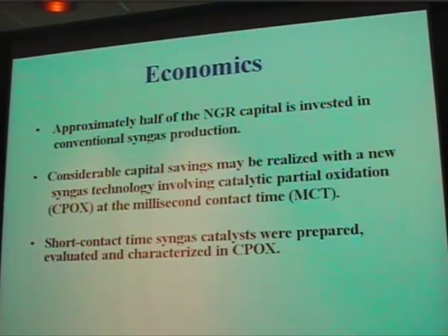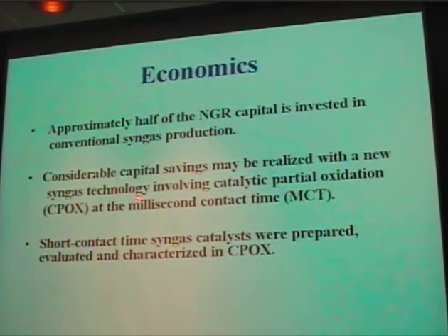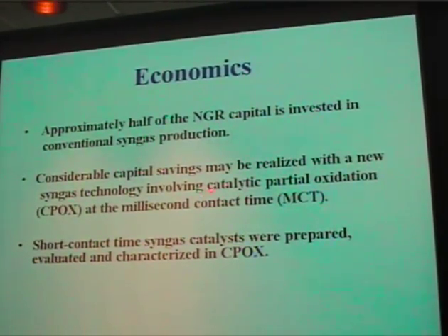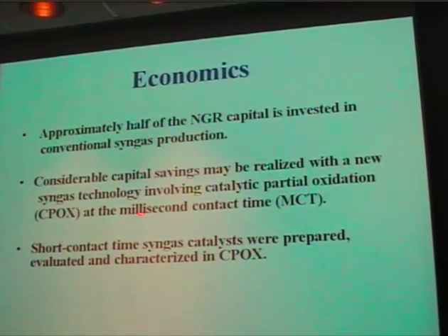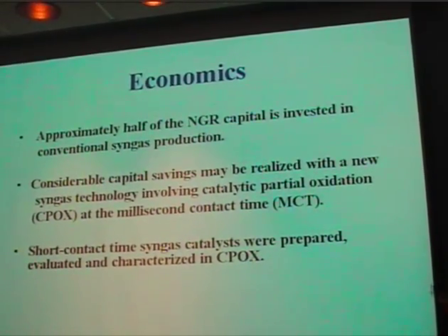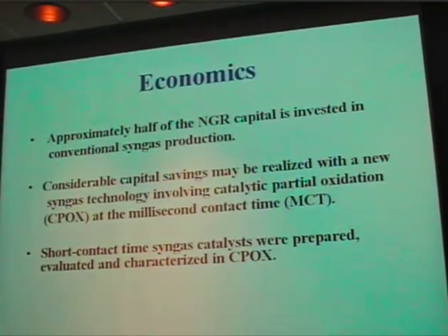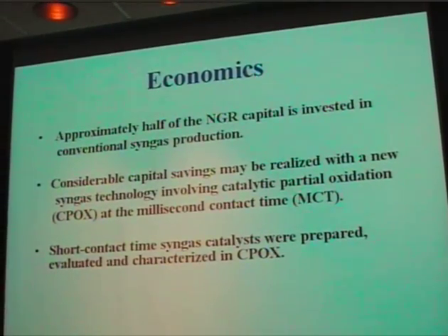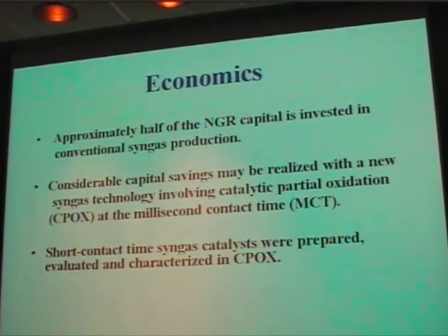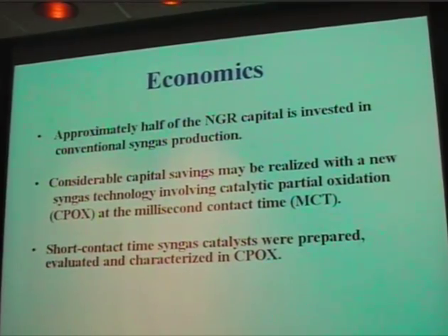And our feeling was that you could save a lot on the technology by conducting it in what we call catalytic partial oxidation at the really short contact time, because then you're really shrinking down your reactor size, you have a high throughput rate. It seemed to be the way to go. So the catalysts that we developed were designed for those purposes, and you'll be hearing more about it.